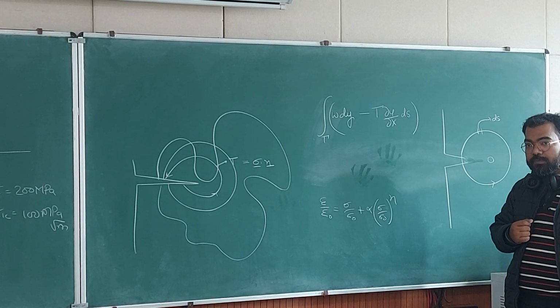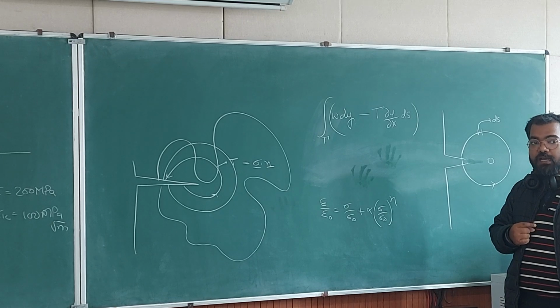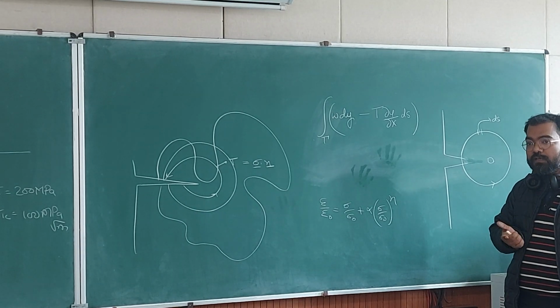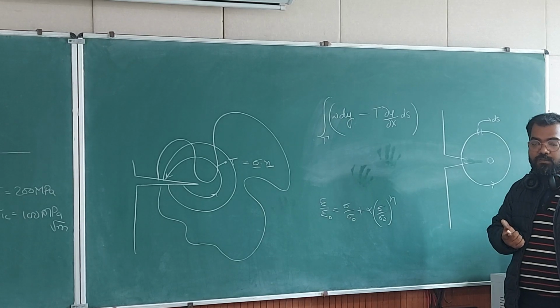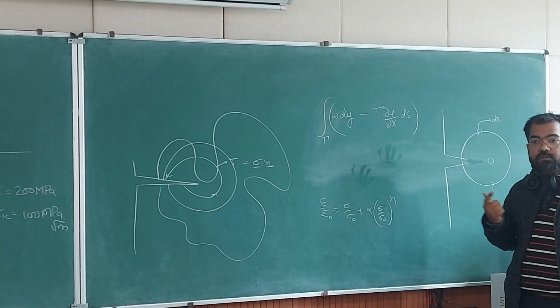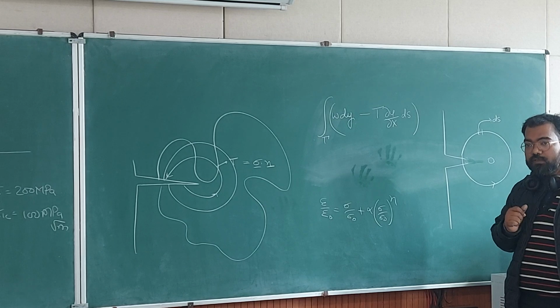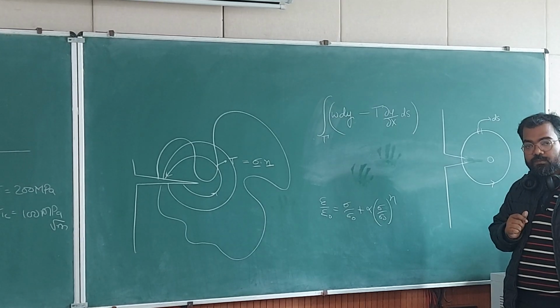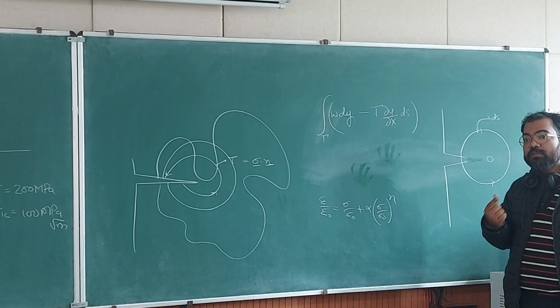That is why it is path independent. Okay, and if the starting and ending points are the same, it is going to give you 0 value, right? So for a closed contour, this line integral is going to give you 0 value always, unless you have something inside it.